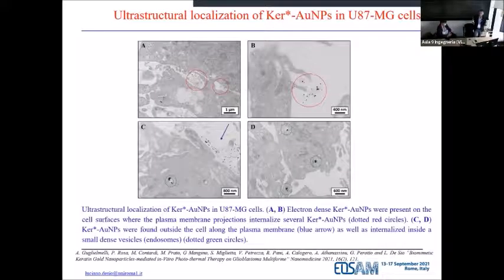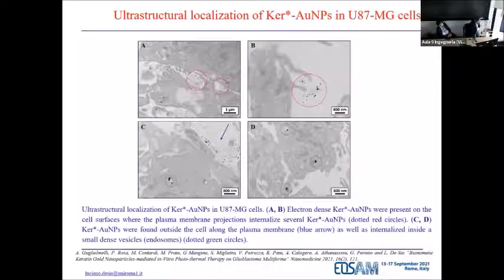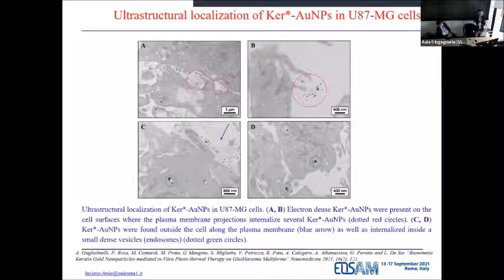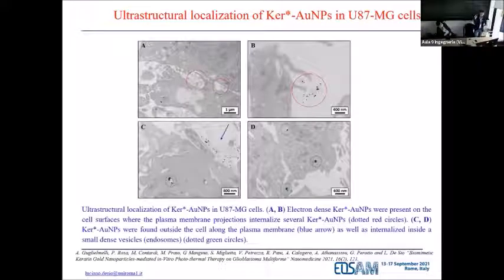And in order to understand where particles are, we did perform ultrastructural localization with a quite high resolution TEM. And you can see that particles are very well internalized by the cells, and we have even particles in the endosome, these very small vesicles, which are here nearby the particles. And of course, we have also particles outside the membrane. It means that very easily they can be internalized, and easily we can uptake those cells with our golden nanoparticles. And I should say that right now we don't have any specific functionalization for targeting. This is something we are addressing. I will give you more details a little bit later on.